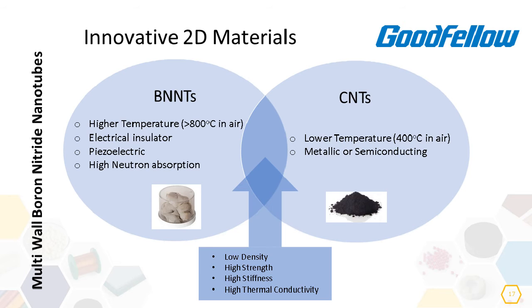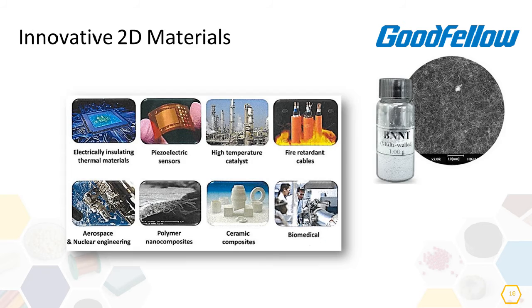Another class of nanomaterials similar to carbon nanotubes are the boron nitride nanotubes. Boron nitride nanotubes are lightweight and mechanically strong like carbon nanotubes. However, they are more thermally and chemically stable than carbon nanotubes. In addition, they have 200,000 times higher thermal neutron absorption capacity than the carbon nanotubes, and they are electrical insulators. This is very important for applications that we are going to see in a while.